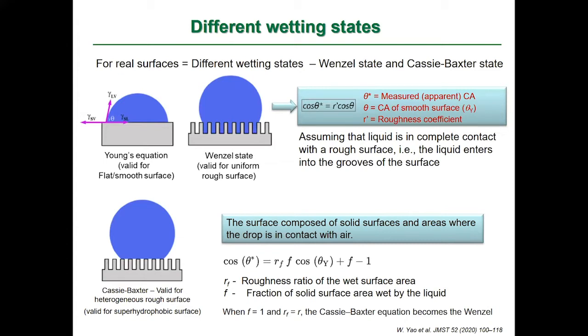So it was Wenzel who considered the roughness parameter to the wettability, and this model assumes the liquid is in complete contact with the rough surface, pinning, and the equation relates the roughness coefficient and the Young's equilibrium contact angle to the measured apparent contact angle. The Cassie-Baxter model is actually the one valid for hydrophobic, superhydrophobic surfaces.